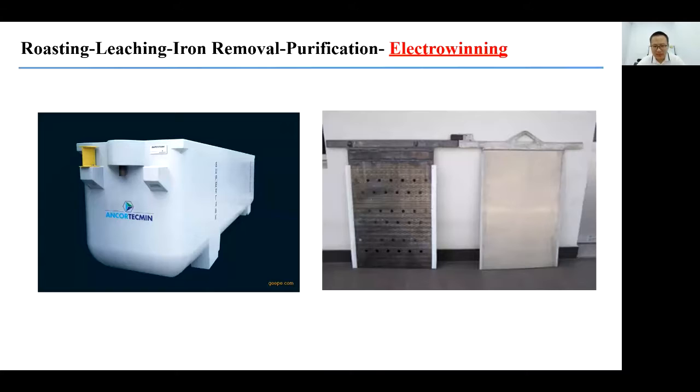Silver is added to increase the conductivity and also to increase the strength of the anode. The oxidized products of lead and also manganese, MnO2, can deposit on this material, which can transfer the electrons and also protect the anodes for longer use, like several days, I think. Okay.